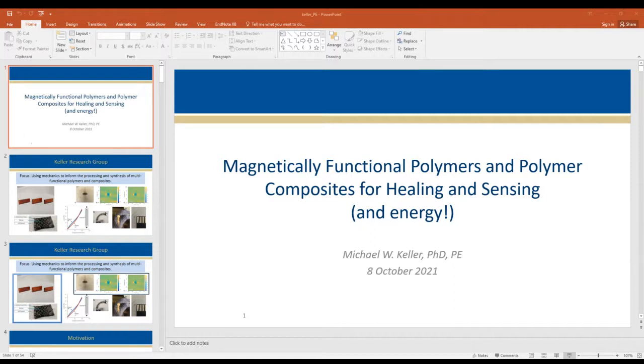So that was fun. What we were able to do is take the base solution and the iron salt solution. You could crush them, and they would form nanoparticles, and then we could embed it and sort of see these nanoparticles. There's a bunch of details associated with tuning viscosity and porosity that I'm not actually going to address, but if you're interested, you can talk. Needless to say, this was a non-insignificant undertaking, but the end game was we were able to produce both of these microcapsules and produce an effect.